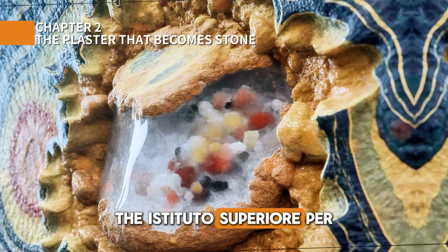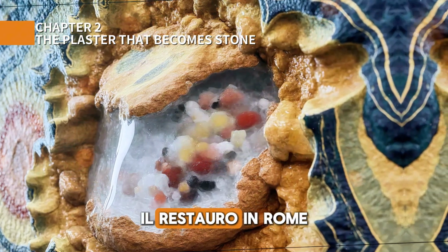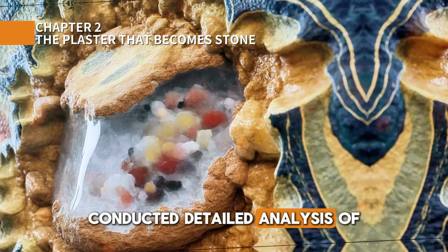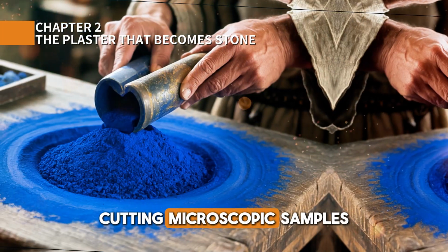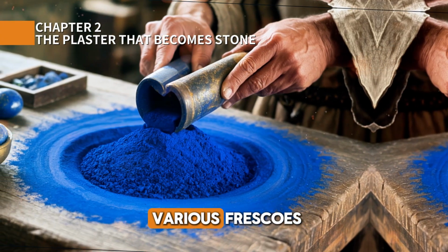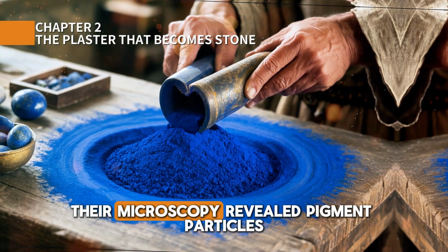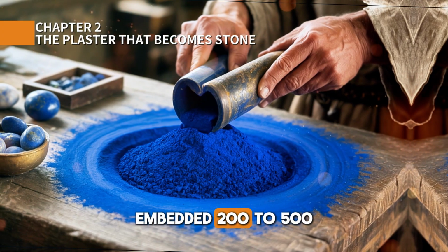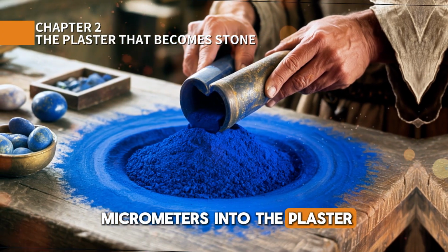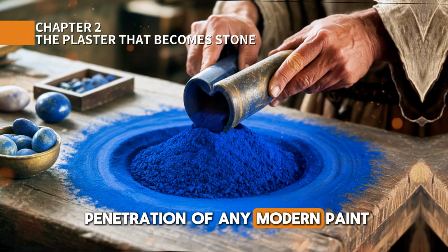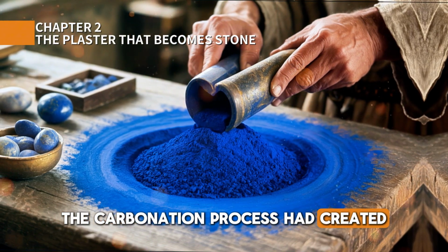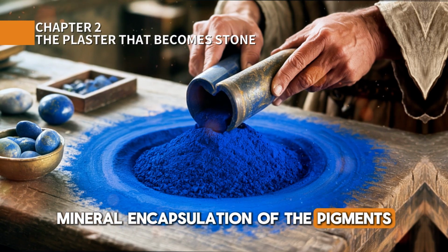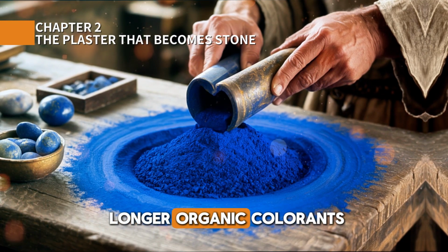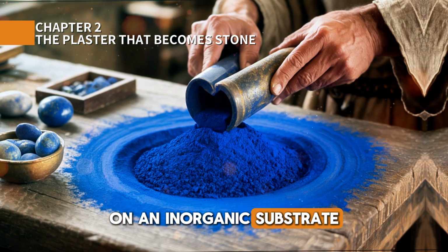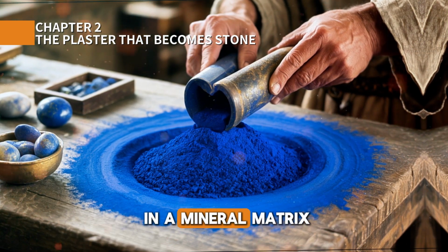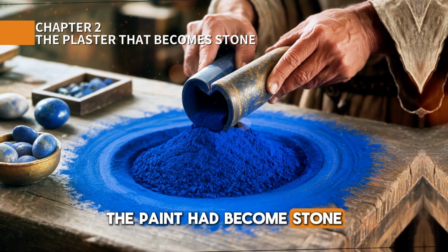The Istituto Superiore per la Conservazione ed il Restauro in Rome conducted detailed analysis of fresco cross-sections, cutting microscopic samples from damaged areas of various frescoes. Their microscopy revealed pigment particles embedded 200 to 500 micrometers into the plaster, far deeper than the penetration of any modern paint. The carbonation process had created mineral encapsulation of the pigments. The particles were no longer organic colorants on an inorganic substrate, they were inorganic inclusions in a mineral matrix. The paint had become stone.